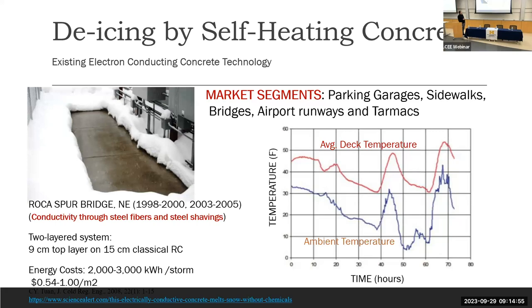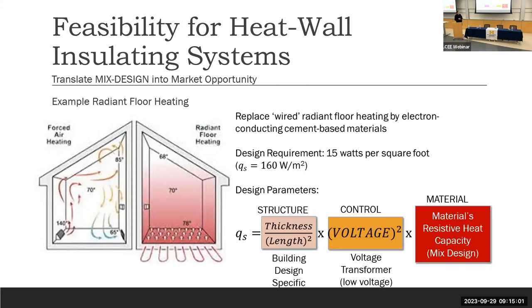You can also think about this for radiant heat application. Again, the problem here is defined. What you need, as a design requirement, is for instance 15 watts per square foot. Then there are three parameters which you are working on. One is a structural parameter, which is thickness over length squared ratio, which talks about the heat propagation within the slab. Then you talk about the control parameter, which is voltage to the power 2, which you can fine tune highly accurately. And then here comes the material design in order to monitor this resistive heating with merely 4-5% of the cheapest possible carbon black, which you can get on the market.